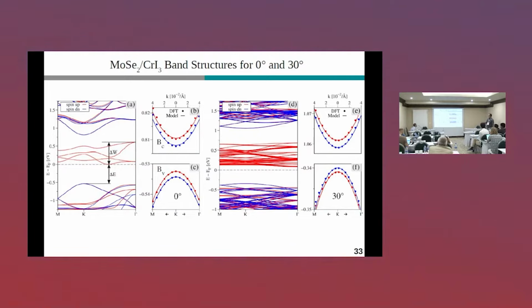And this is a calculation without spin-orbit coupling to really resolve the proximity exchange alone. Now if you zoom into the band edges, you will find a splitting of the conduction band edge and the valence band edge like this. The spin ordering is the same, and we characterize this splitting by a parameter B_C and B_V. And if you then go to the 30-degree case, you find that the conduction band splitting remains, the spin ordering remains, while the valence band switches sign.